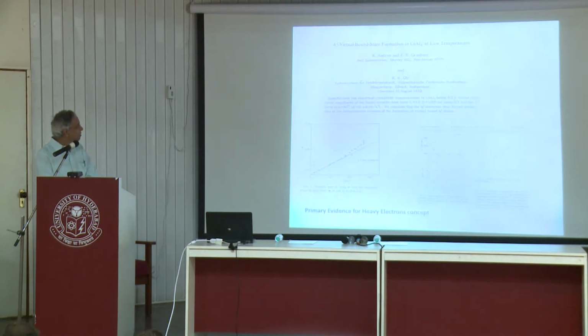In other words, I would like to say that the 4f orbital need not have a stable 4f configuration. It can vary as a function of time. When you take a time average, that number also can be temperature dependent. Therefore, the concept of valence which you talk about in the textbooks is completely different. It's not a very stable number. So it's a very sharp valence change here. Now, till now I gave examples of europium, which can undergo some kind of 4f electron delocalization, samarium, and things like that.